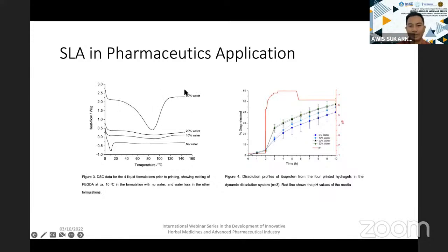So let's say you have a very high percentage of water, what you can do is dry your sample first, or in this case heat up the sample to 100 or 120 degrees, leave it for a while, then cool it down, and rerun it again. So the first process is to remove the water, and after that is the actual process where you see if any transition temperature happens somewhere in this range.